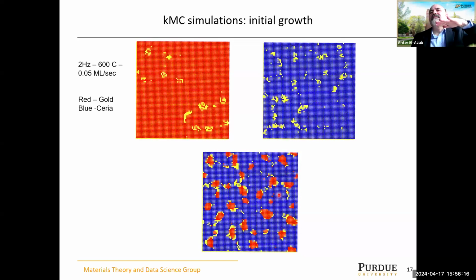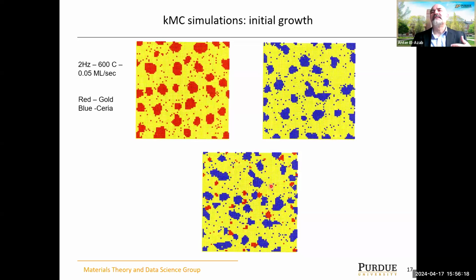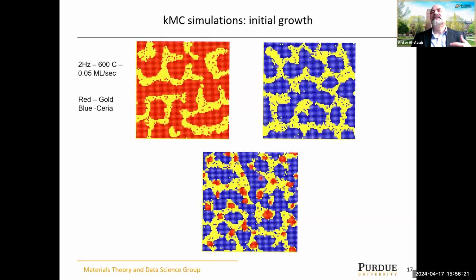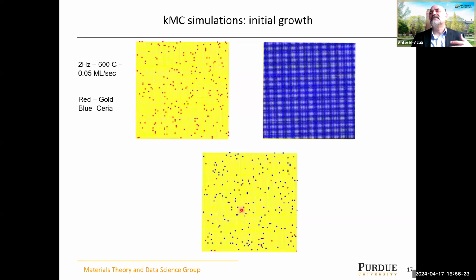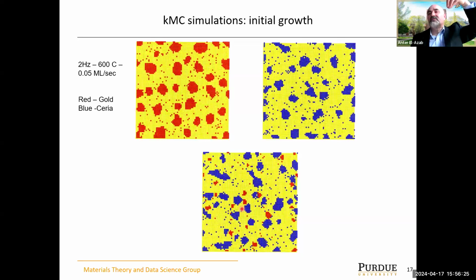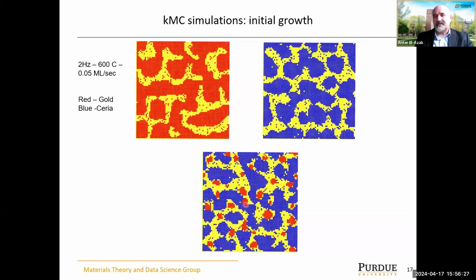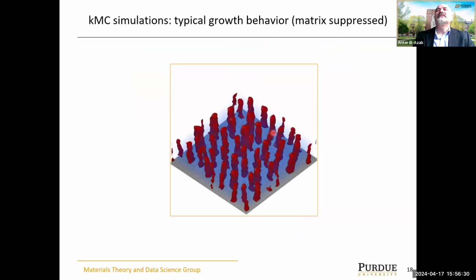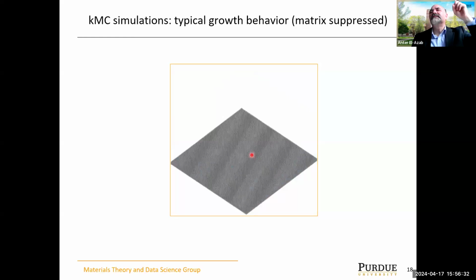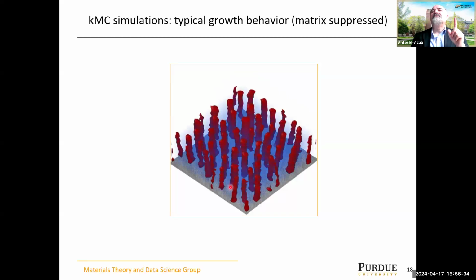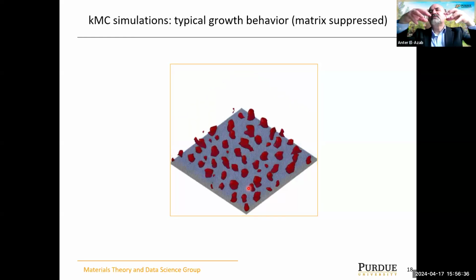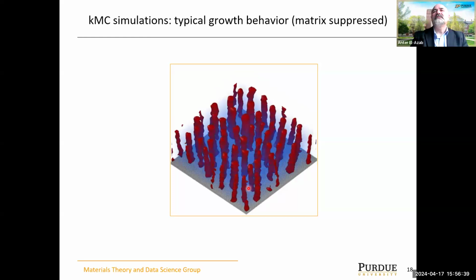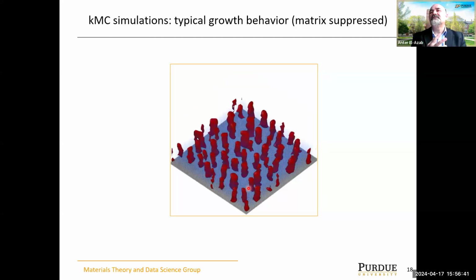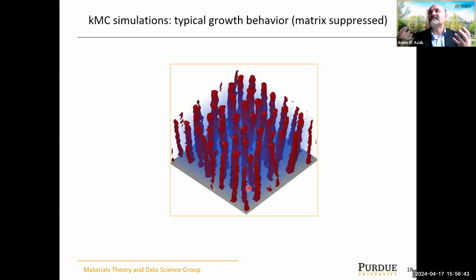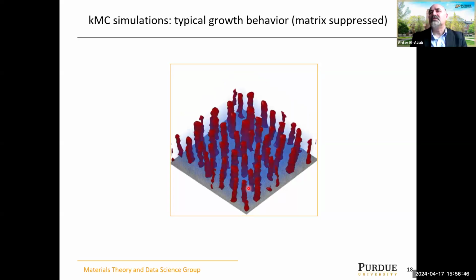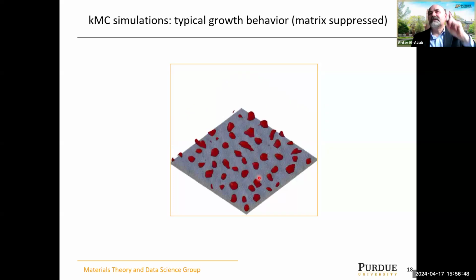The next layers are going to recognize that you have these islands of gold in the blue phase here, and then the gold is going to attract gold and grow vertically here, and that's what we call the vertically aligned nanocomposites. Gold sort of attracts gold to grow in that vertical direction because of thermodynamics. It likes to phase separate from ceria. It doesn't mix with it, so it has to go to gold and grow these things vertically.